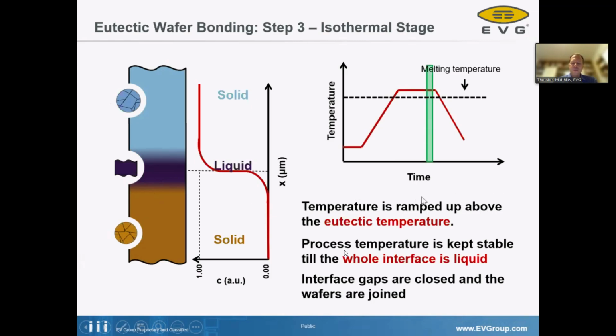In this case, the cooling down has to be very accurate, because when cooling down a liquid, if this would not be homogeneous across the entire wafer, it would be very easy to integrate some stress into your device. And especially for a lot of MEMS devices, if you already create a stress by the package, then you probably already create some drift in your sensor. So here the cooling, especially the very first part, going from the liquid phase to the solid phase, is very important for eutectic wafer bonding, that you do it very, very controlled.